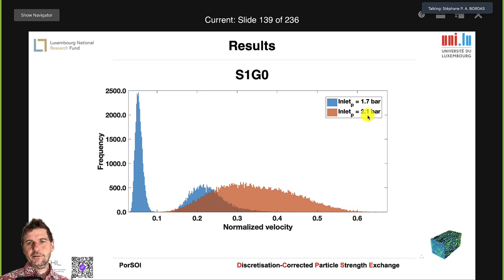All right, so now let's compare the two approaches. So here we have a pressure which is 1.7 bars and here a pressure of 2.1 bars. So as you can see, the 1.7 bar pressure leads to quite a lot of very small velocities inside, which you can expect because the pressure is less. So therefore you have a lot, meaning there is a peak in small velocities.